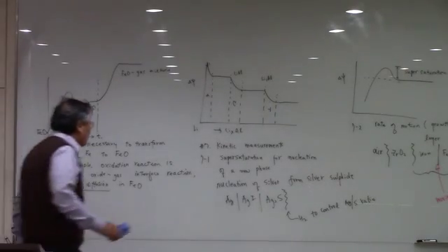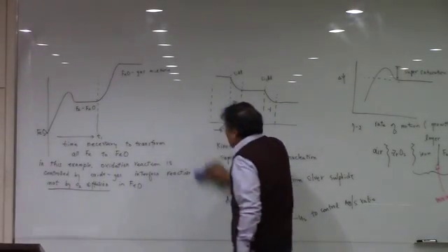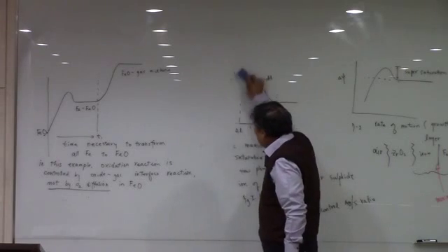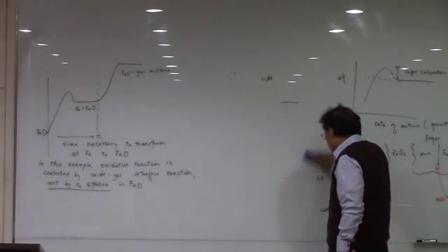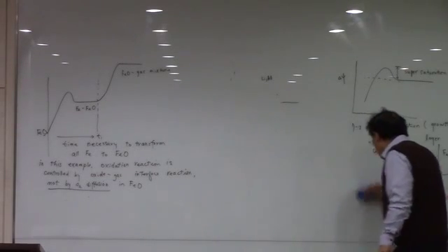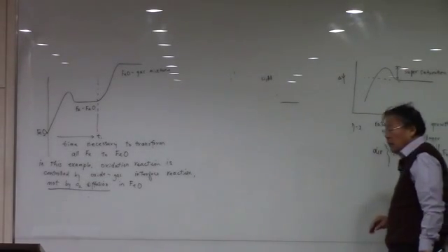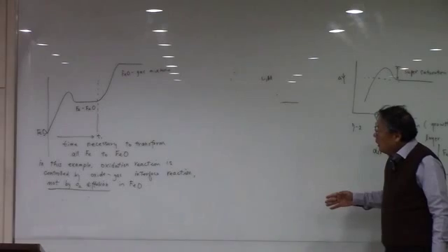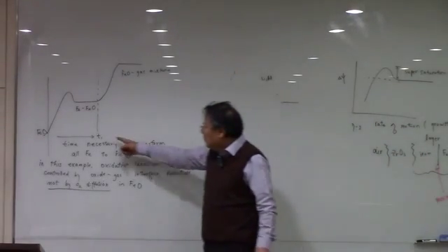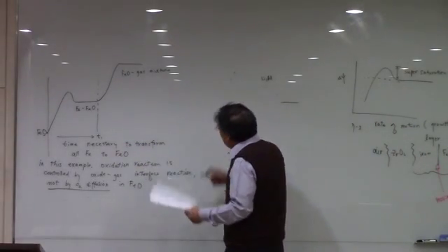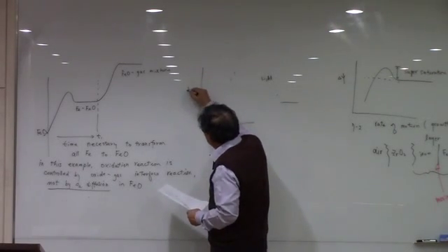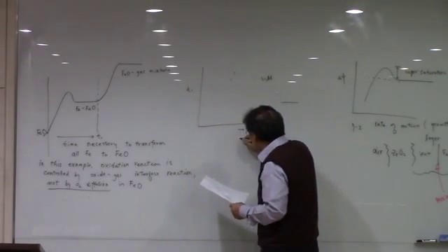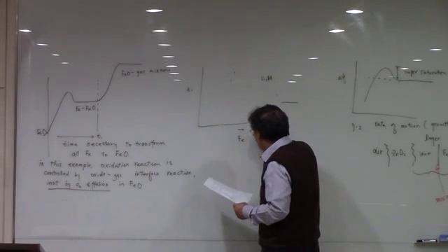You use all different thicknesses of Fe and then make the surface be oxidized with the gas mixture, and then measure the time T1 with a different thickness. Okay, this is the T1 and this is the Fe thickness.